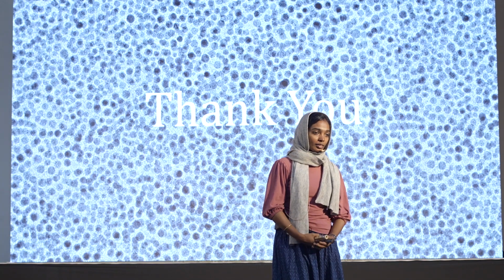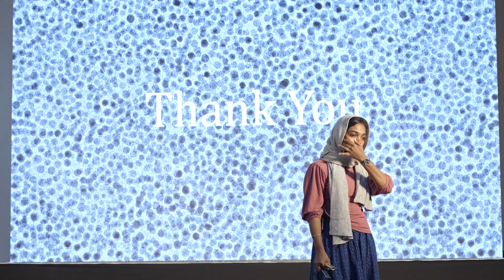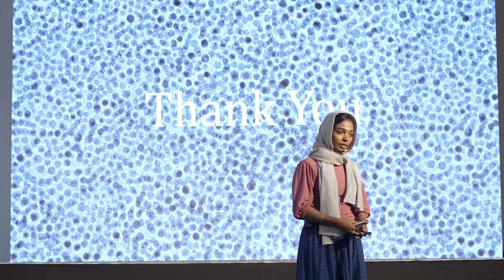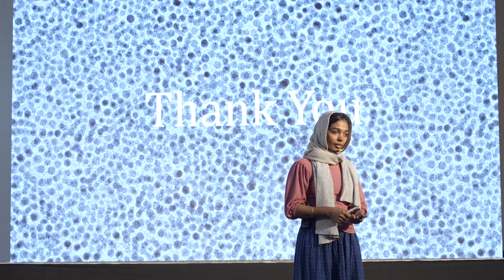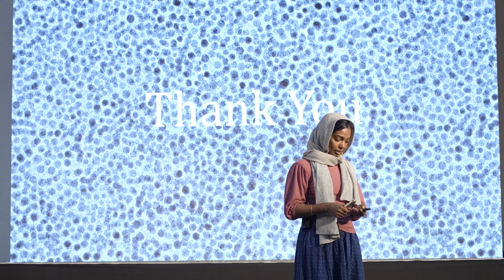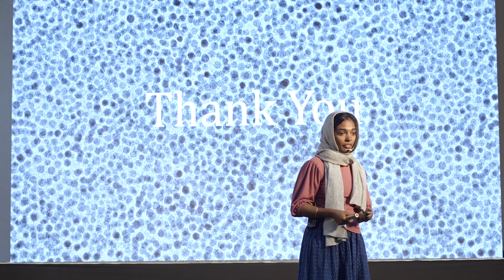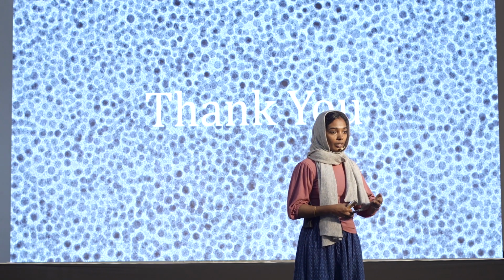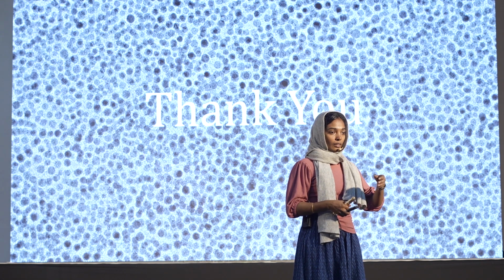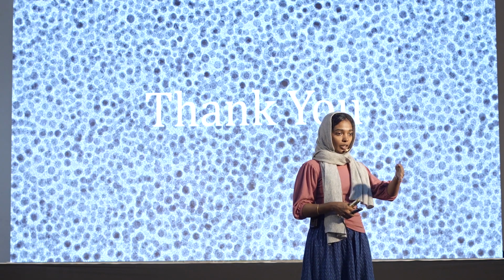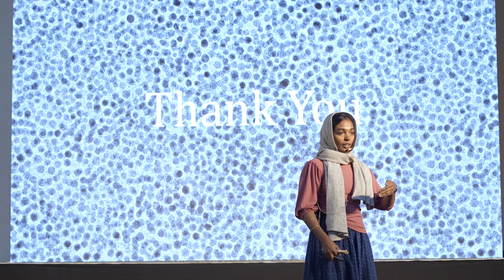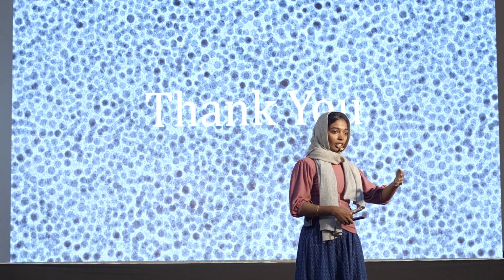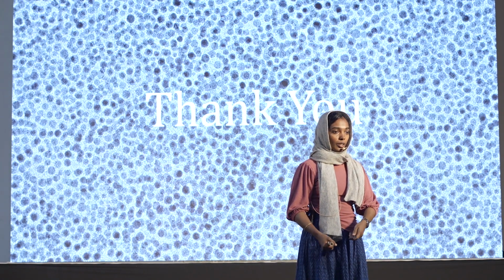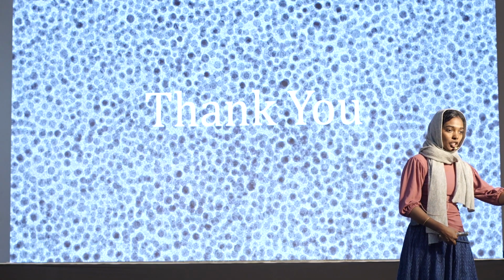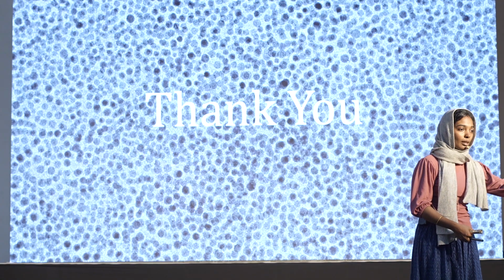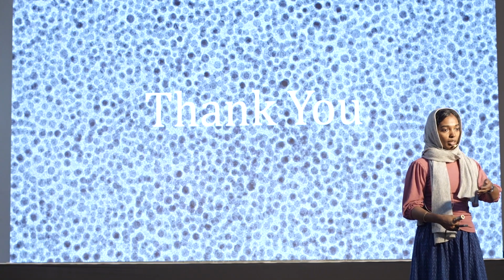Very nice work. So you mentioned, I think, in terms of recyclability, that gold decorated platinum nanocluster is better than the other two, right? Not recyclability, reactivation, ma'am. Actually, we have done that experiment running in the methanol containing sulfuric acid. Okay. And while we are recording a CV, then again we take the same electrode and run a reactivation in the methanol free electrolyte for some cycles, and again we check the methanol oxidation.